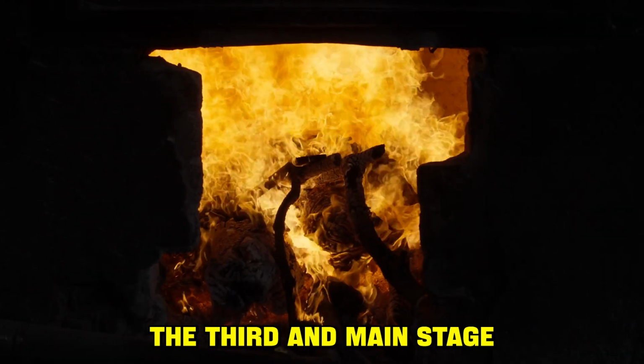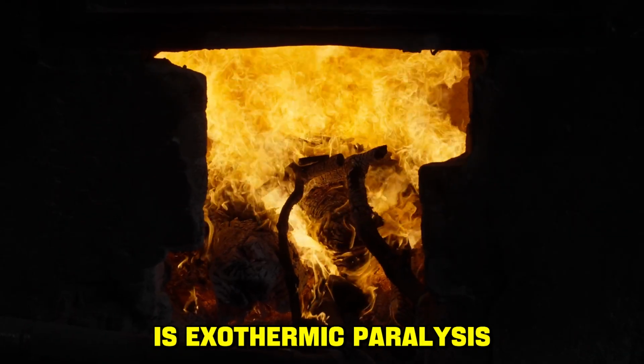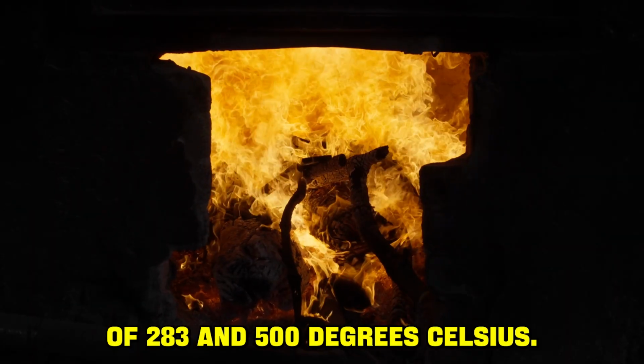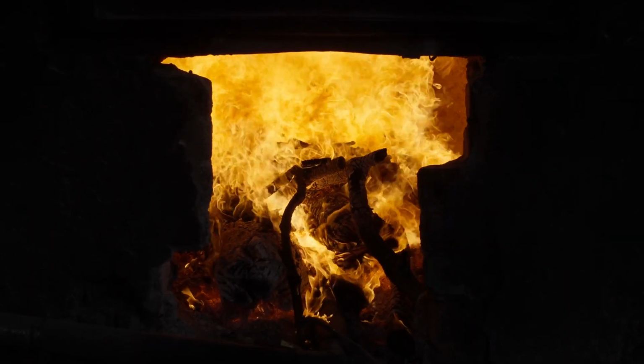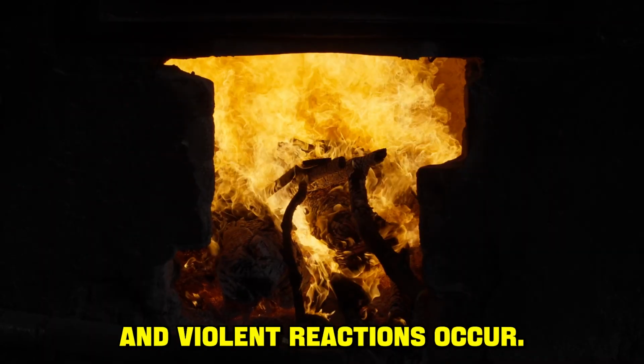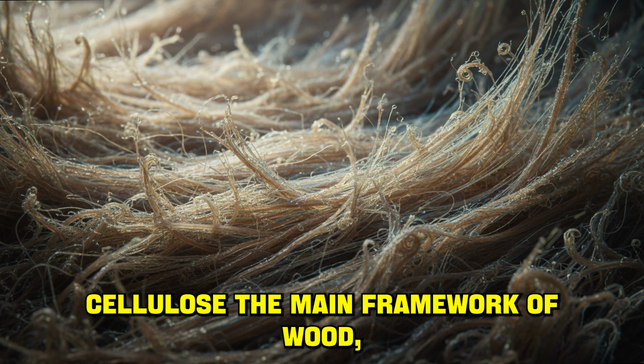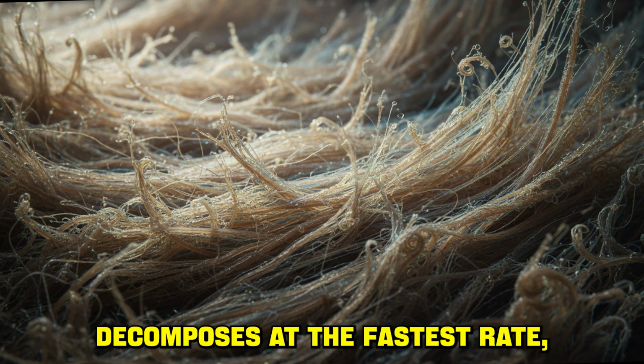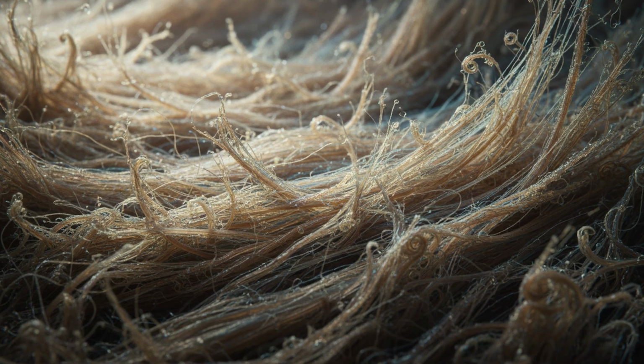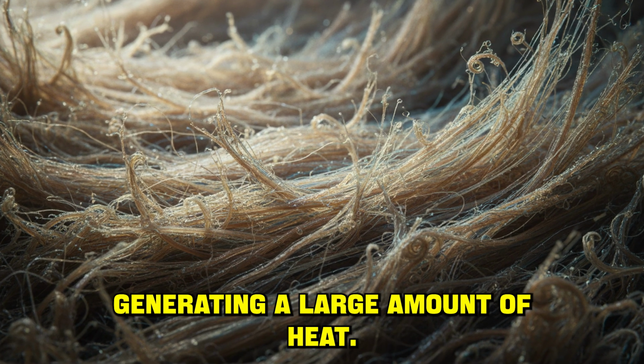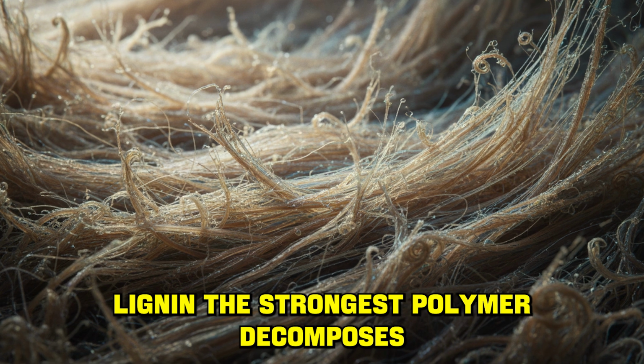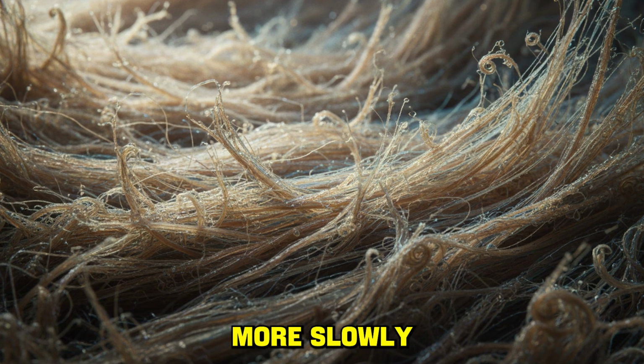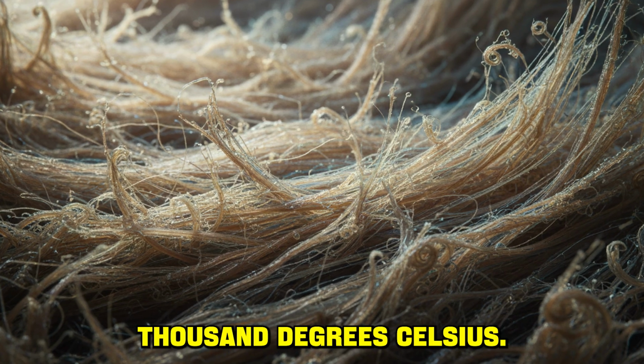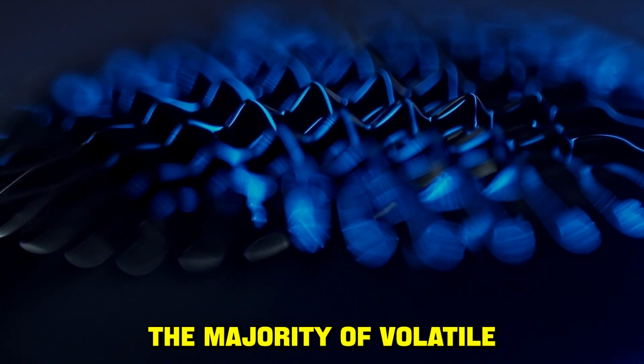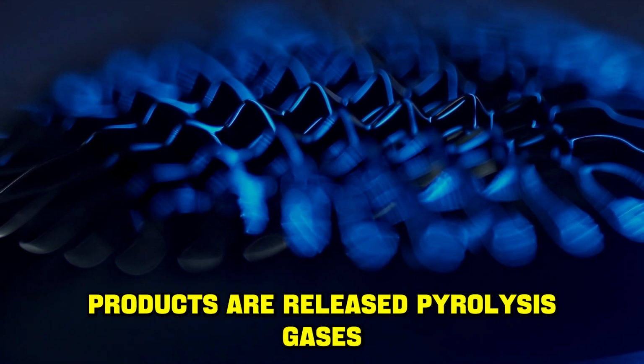The third and main stage is exothermic pyrolysis, occurring in the range of 280 to 500 degrees Celsius. This is where the most intense and violent reactions occur. Cellulose, the main framework of wood, decomposes at the fastest rate, generating a large amount of heat. Lignin, the strongest polymer, decomposes more slowly and over a wider temperature range, up to 700 degrees Celsius. At this stage, the majority of volatile products are released.